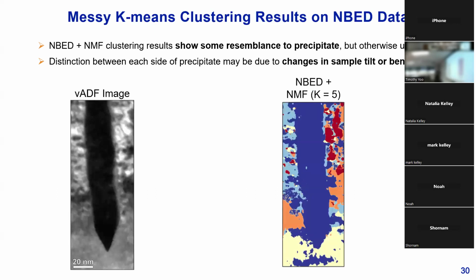And so here we see the image of the initial test region again. And here's the initial result. So there's a couple of things to note here. At first, we see that it's kind of messy, but what does that actually mean physically? So first, we see that there's k equals 5, as we just saw, even though we're only expecting 3 phases. Okay, so that's already kind of not a great start.